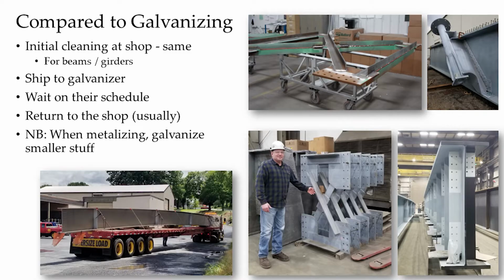So a key thing that we recommend at High Steel is don't metallize the small stuff. Metallizing has become popular, and some folks look at it as a way to get galvanizing on bigger stuff. Galvanizing is a really excellent coating. You can't galvanize stuff that is too big for the kettles. So metallizing has kind of caught on as, oh, well, it's like sprayed on galvanizing. In a way it is, because it is sprayed on zinc, but it's nothing like galvanizing in terms of how the coating is formed. Galvanizing forms by interacting with the iron in the steel to produce grains that grow off the surface, versus spraying on zinc. Metallizing is a good coating, but to try to say it's the same as galvanizing, really it's not.